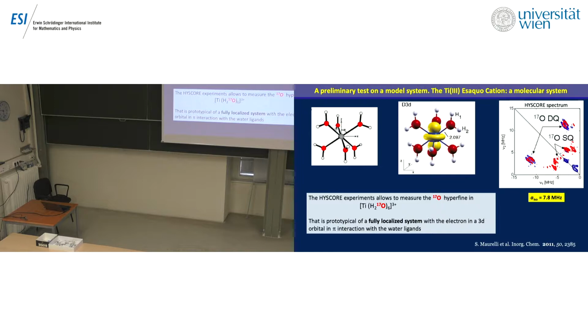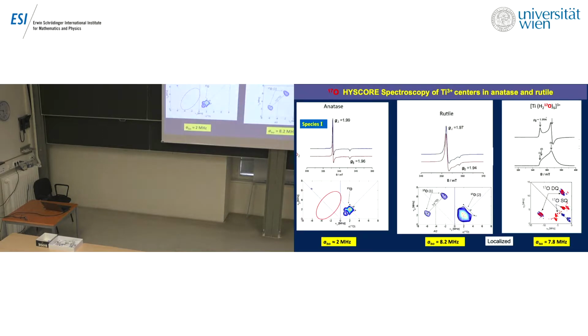It's extremely tiny, it's really nothing, okay? And this is a true localized system. So now look at what we had in the case of our TiO2 system. This is water. This is a rutile interstitial site, similar thing. You have to see this quadrant, and this separation is important. 7.8, 8.2 is the same, so strongly localized system in rutile. And this is an interstitial site.